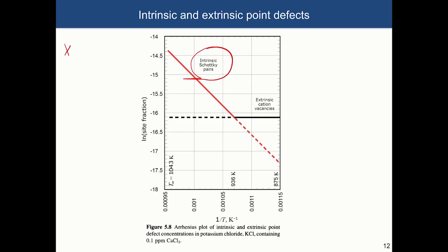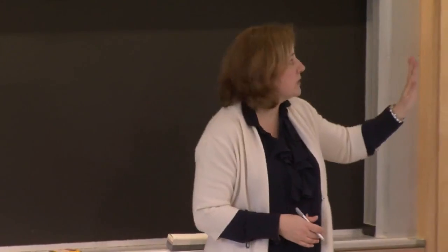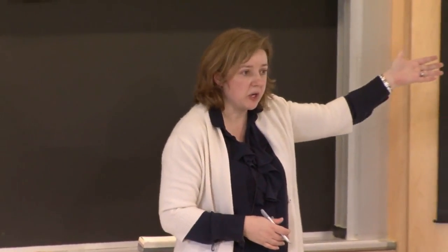So we mentioned that, for example, the concentration of the intrinsic types of defects will be the exponential function that depends on the energy that is required to form that intrinsic type of defect over kT. Right? And again, what these intrinsic type of defects can be, these can be interstitials, they can be vacancies, they can be combinations of Frenkel, Schottky, etc. So each of these defects will have an associated energy that is required for that, and you can calculate that. But they all have the same, this Arrhenius type of behavior. They're all dependent on the temperature, and you can, in principle, predict them.